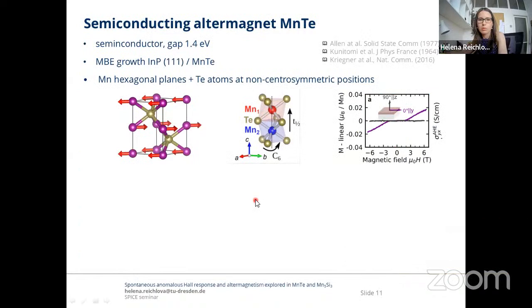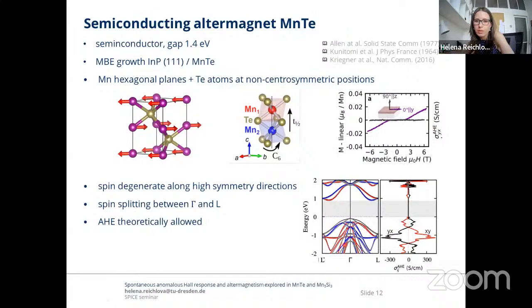This is what makes this material an altermagnet. When looking into band structure calculations, the spin up and down is degenerate along the high symmetry directions. However, going away from this, for example, between gamma and L, we see that the spin splitting is clearly present and alternating. Also, the anomalous Hall effect, when it's theoretically calculated, is allowed.